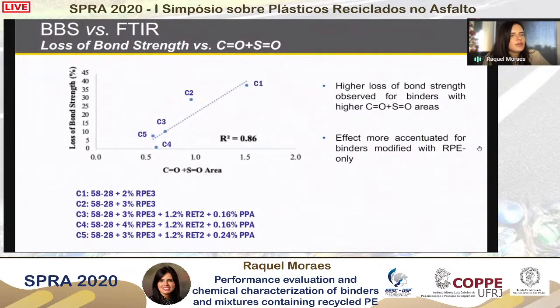And we have here an evaluation between the BBS results and the FTIR, where we can see that a higher loss of bond strength was observed for binders with higher carboxylic and sulfoxide areas, as mentioned before, and this effect was way more accentuated for the binders that contain the recycled polyethylene by itself.